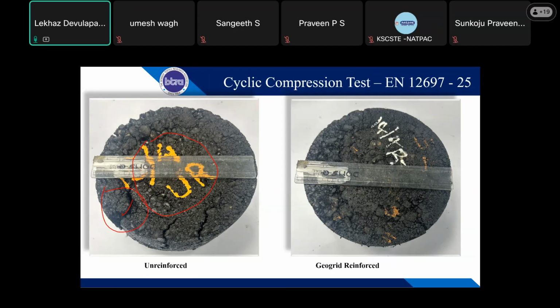And then this is a specimen with a geogrid reinforcement. You can see slight cracks, since at 1400 kPa the specimens had already failed, but they were still not that visible when compared to the unreinforced or control specimen.